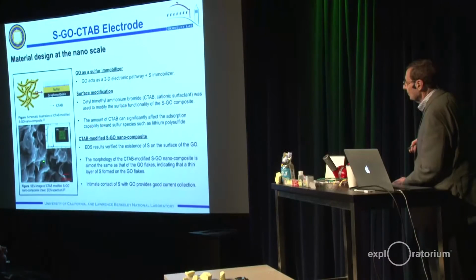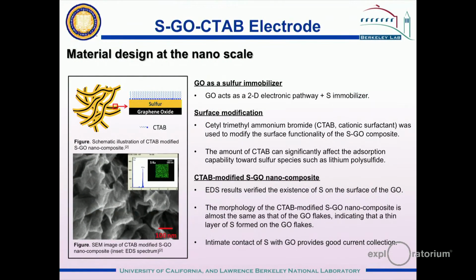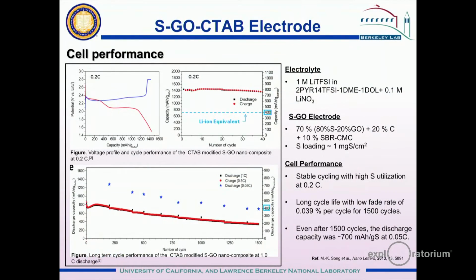This is a scanning electron micrograph that shows the flake-like structure of the graphene oxide, which is covered with the sulfur. And this green area here shows that all of the surface of the graphene oxide has been coated with the sulfur material. So that's what we're looking for. A very highly conductive material on a nanoscale that we can use in making our sulfur electrodes. So we combine our sulfur graphene oxide here with some carbon to give us additional electronic conductivity and a binder. This SBR is styrene butadiene rubber. So it's a rubbery binder that allows the electrode to expand and contract as we charge and discharge the cell.